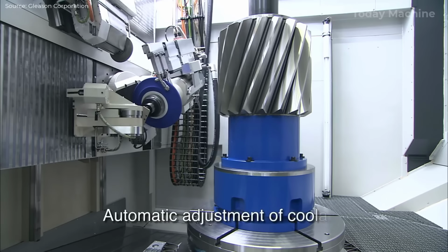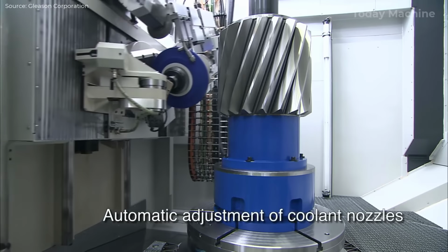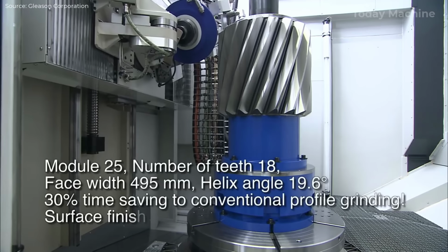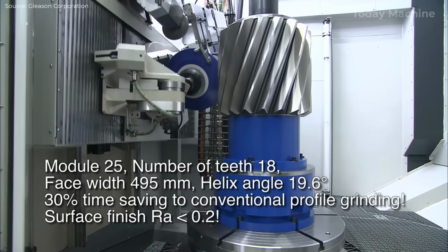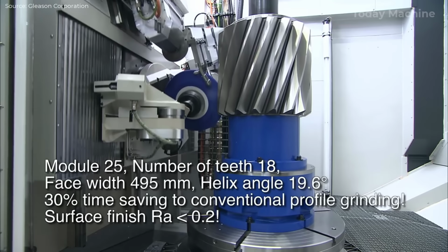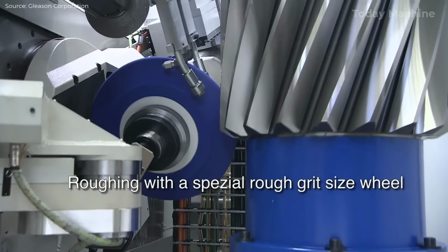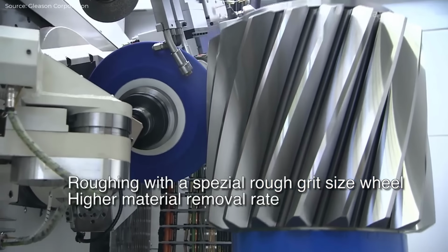For a gear with a module of 25, 18 teeth, a face width of 495 mm, and a helix angle of 19.6 degrees, the machine can achieve a 30% time saving compared to conventional methods, with a surface finish of Ra less than 0.2.